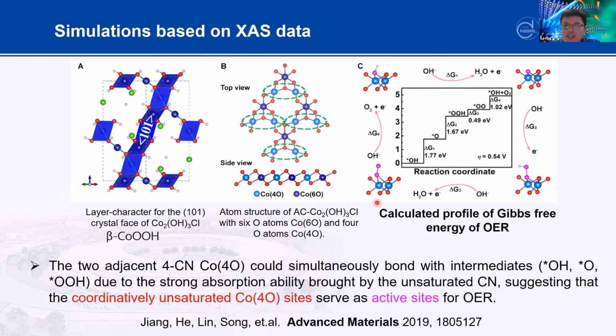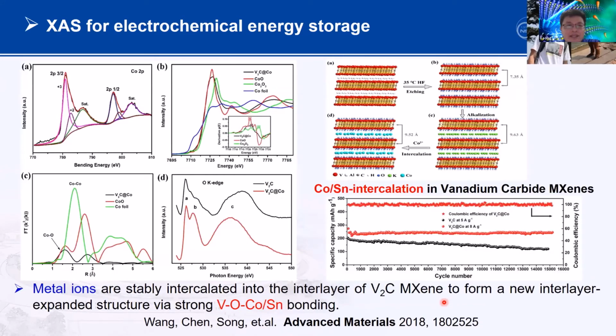By the simulation of the Gibbs free energy for the OER, you really find the real active site is this, not the cobalt with 6 oxygen, but cobalt with 4 oxygen. So we can clearly suggest that the coordinatively unsaturated cobalt 4 oxygen site serves as the real active site for the OER. This is what we understand by XAS combined with the simulation. So the last example is this.